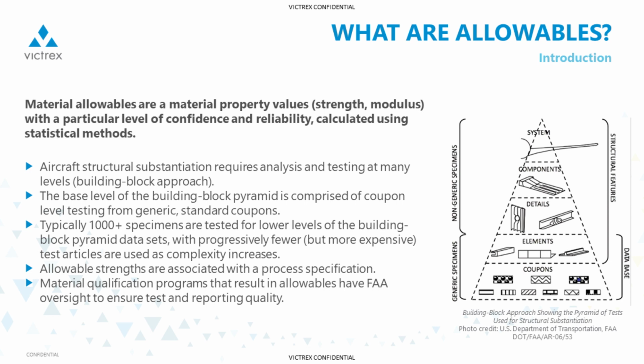In short, material allowables are material property values with a particular level of confidence and reliability calculated using statistical methods. Any aircraft structure substantiation requires analysis and testing at many different levels. The image on the right is an example of the building block approach, where you have coupons and small articles on the bottom and move all the way up to system level test. The lower levels of the building block pyramid are where the bulk of the testing takes place, using generic, standardized testing, with 1,000 plus specimens tested. As you move up the pyramid, the tests become more and more expensive and more complex.